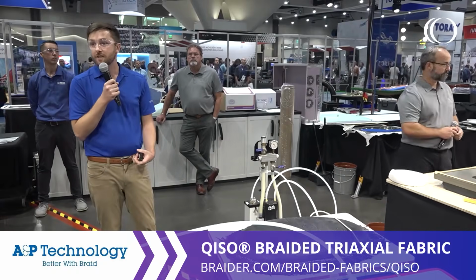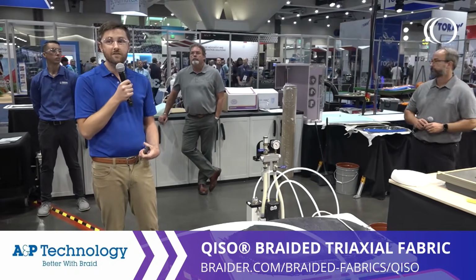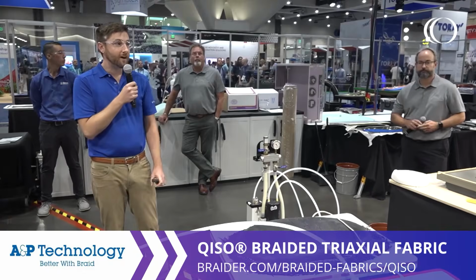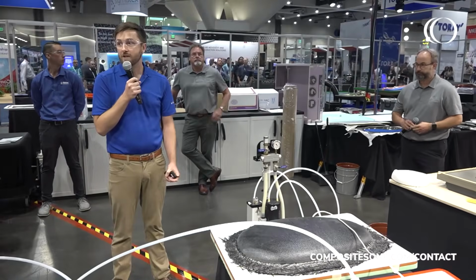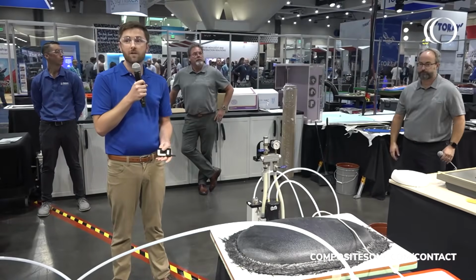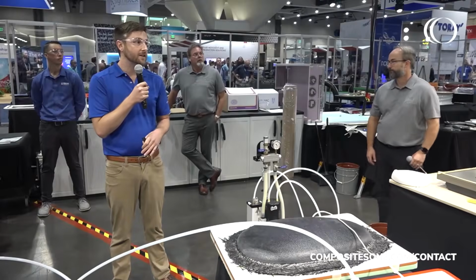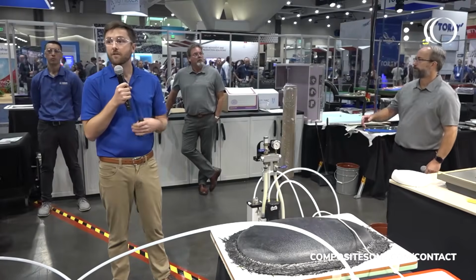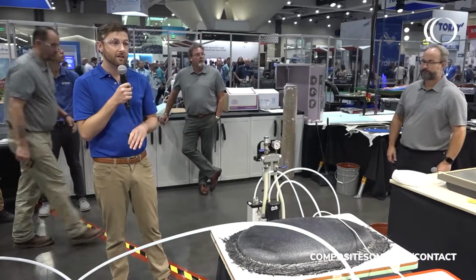Qiso is a really unique reinforcement. It's a braided triaxial carbon fiber fabric with fiber orientations of 0 degrees off the roll and then plus and minus 60 degrees all in a single layer. So what that means is you have a quasi-isotropic structure all in a single ply.